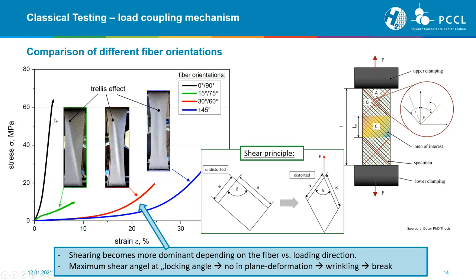And what we found here was also so-called wrinkling of the material. You see it here also with this trellis effect. This is based on the shear principle, because when you reach this maximum shear angle, then no in-plane deformation is possible anymore. And therefore, you end up with this wrinkling, and finally with the break of this setup or of the material.